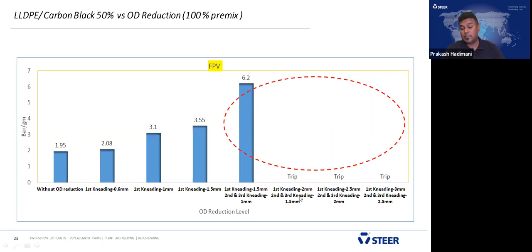And afterwards, in the case of first kneading 2 millimeter and 2.5, 3 millimeter, that shows the filter pressure value was tripping because its dispersion quality was very poor. That gives an indication.